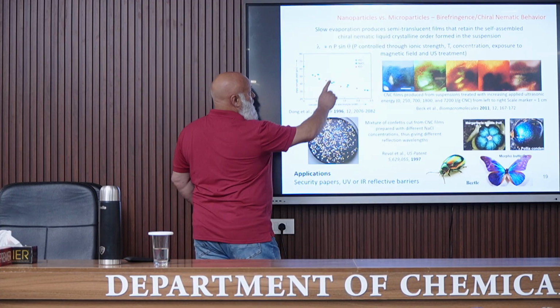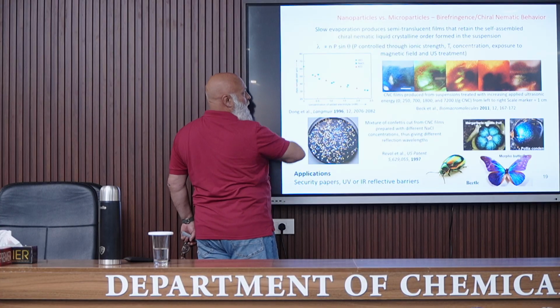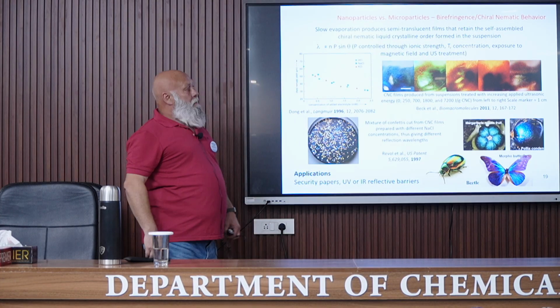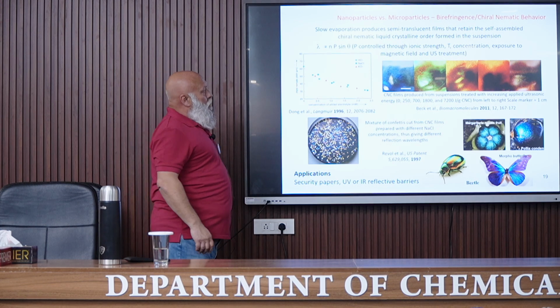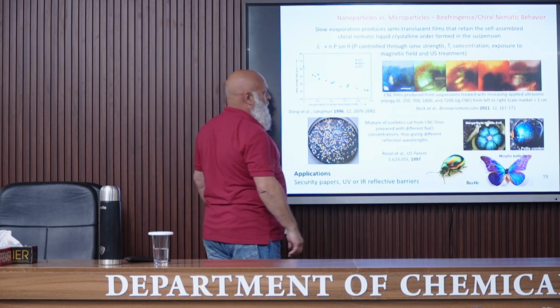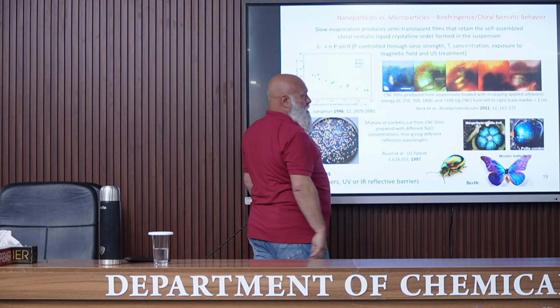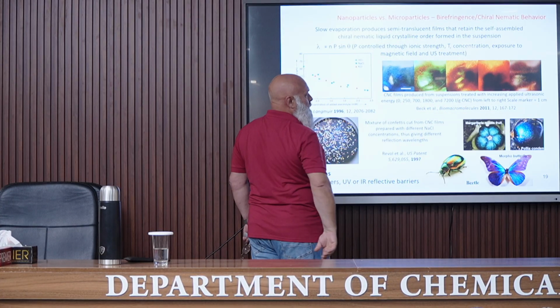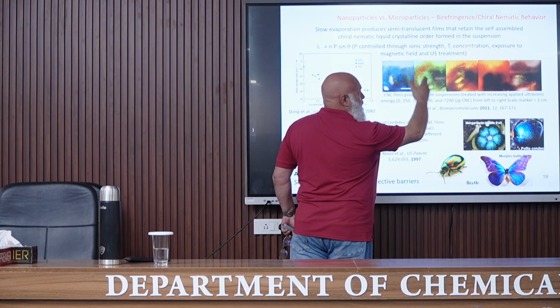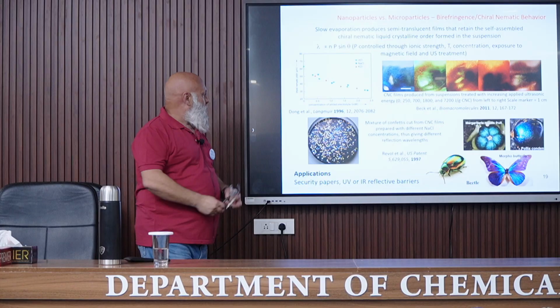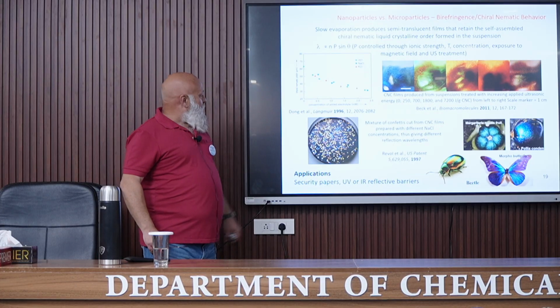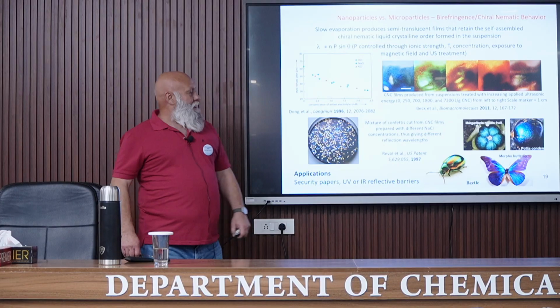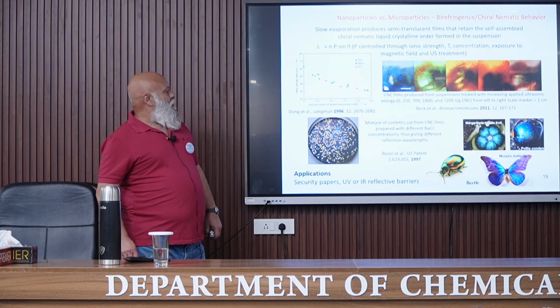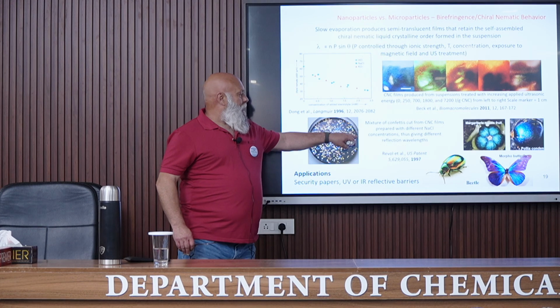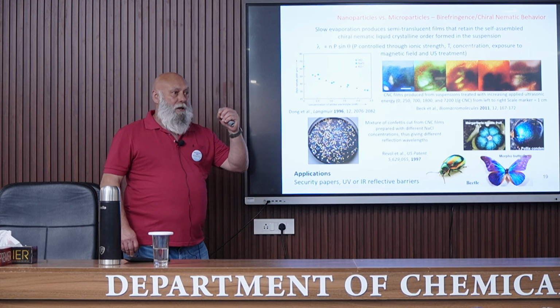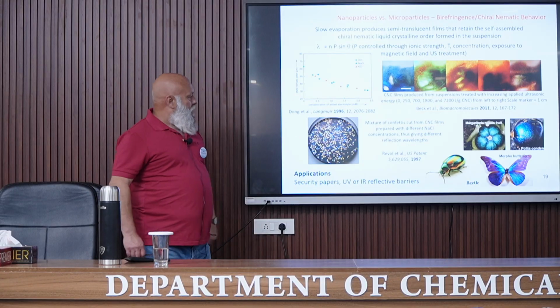And so, this pitch can be controlled through the ionic strength. It can be controlled by temperature, by the concentration, by the exposure to magnetic field or ultrasonic treatment. You can see here a suspension that has been treated using an ultrasonic treatment with different energies, and it changes the color of the film. I like this figure, this picture here. So it's a mixture of confetti that were cut from cellulose nanocrystal film, prepared with different electrolyte concentration. They change the pitch and then the color. And so we obtain these different colors.